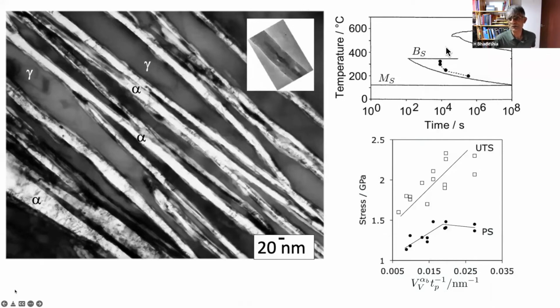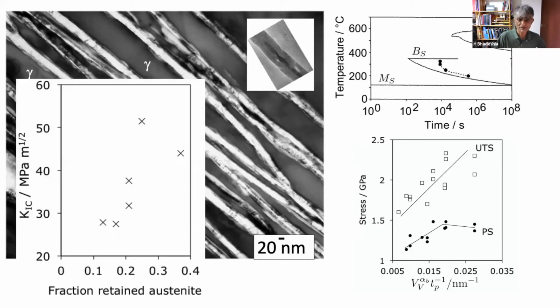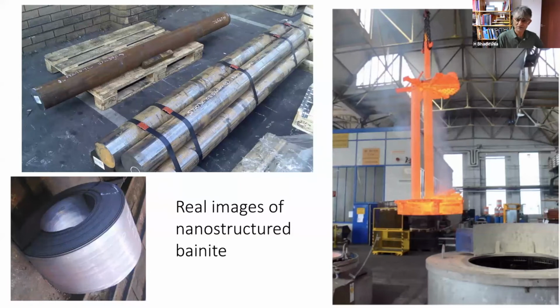And these were our calculations of the kinetics of transformation, and these were the measurements. We have impressive properties. You can get up to 2 point something gigapascals of strength and impressive values of toughness as well. And that's what that armor that I showed you, ballistic armor that I showed you at the beginning, is made of. And these are real pictures of the nanostructured bainite being heat treated and produced.